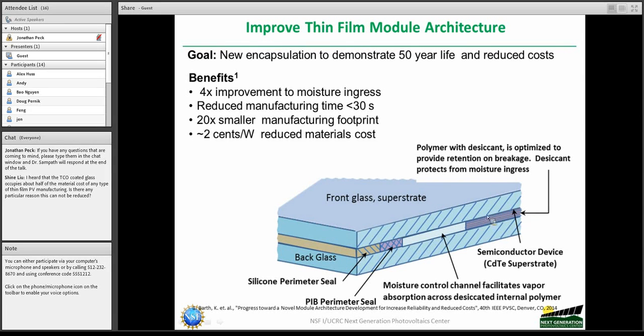And here is an optimized polymer material containing desiccant so that you can have this 50-year life. And in addition to the improved life, there are many other benefits. This has got a 4 times improvement to moisture ingress, reduced manufacturing time. This whole thing can be put together within 30 seconds compared to the current encapsulation process that takes 15-20 minutes or so, and a much smaller manufacturing footprint area.